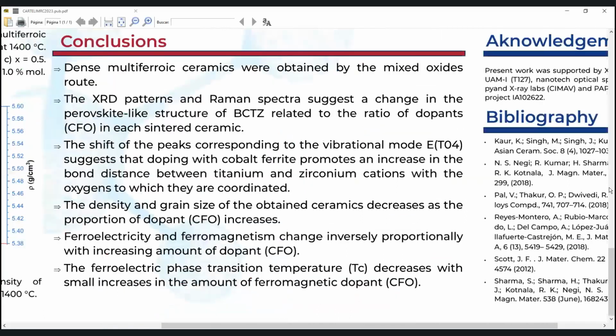In conclusion, dense multiferroic ceramics were obtained by the mixed oxide route. The XRD patterns and Raman spectra suggest a change in the perovskite-like structure of BCTZ related to the ratio of dopants in each sintered ceramic. The shift of the peaks corresponding to the vibrational mode E(TO4) suggests that doping with cobalt ferrite promotes an increase in the bond distance between titanium and zirconium cations with the oxygens to which they are coordinated.